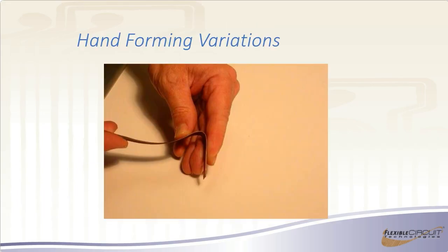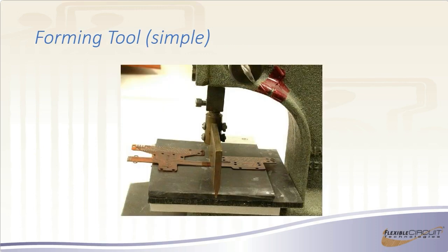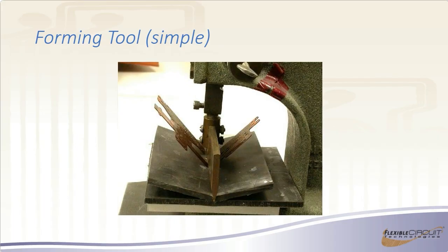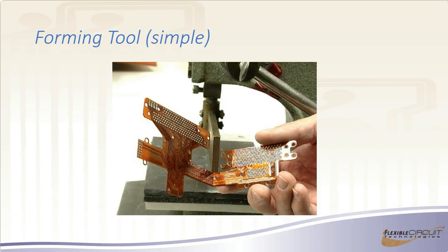We typically like cold forming. It's a less expensive process, and it's less damaging to the flex circuit. When I say cold forming, though, typically you don't want to do it like this or like this. Here's one application. It's very simple. It's just an arbor press with some high durometer rubber and a known radius on the edge of the forming tool. You force that into the rubber, and you can get a repeatable form each time.